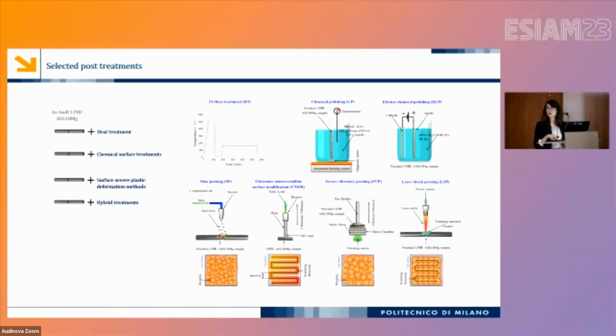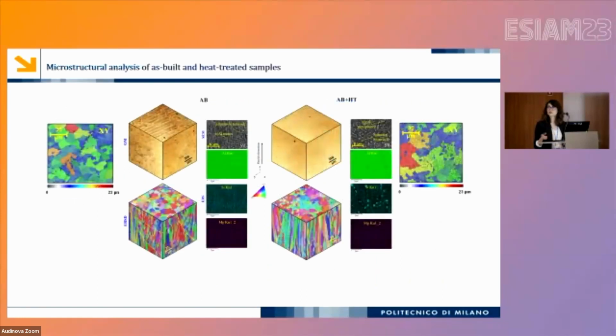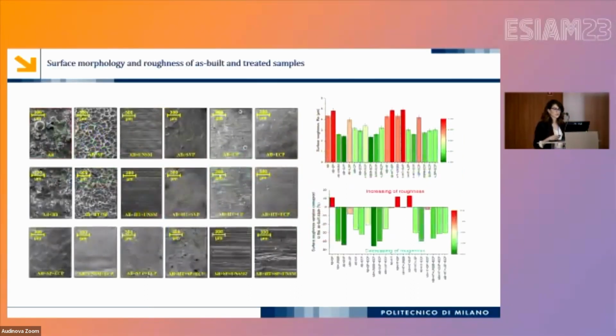Starting from the heat treatment, we see the clearly inhomogeneous microstructure in the as-built condition becoming much more homogeneous after heat treatment. The laser traces are faded, and there is a slight grain coarsening, but in general the microstructure becomes much more homogeneous after the heat treatment.